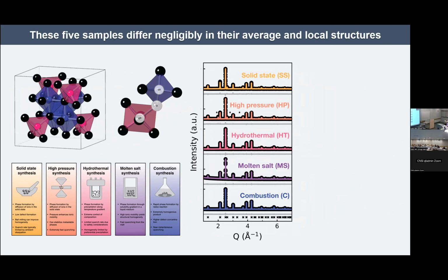When we produce these materials, the first thing that we see is that at the average level, they are equivalent to one another. If we do X-ray powder diffraction on our five different samples, we see negligible variance in their lattice parameters and their adjustable structural positions. These samples look really equivalent. There are minor differences in peak widths, but no more than you would see in two samples prepared with batch-to-batch variance.